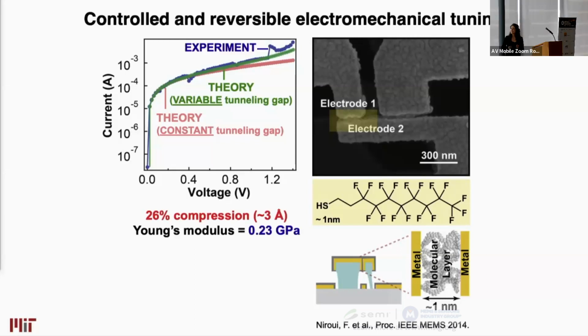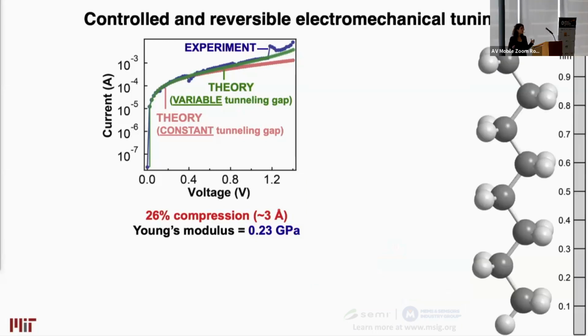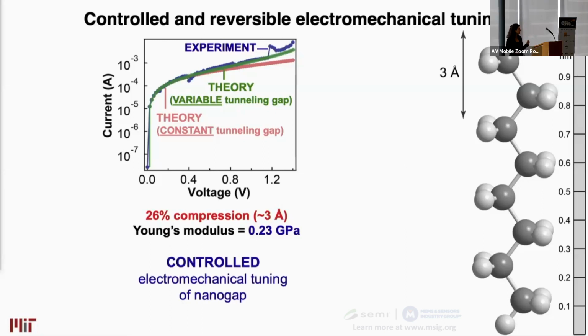Now, in getting this best fit, we estimate the Young's modulus of the molecular layer to be on the order of 0.2 gigapascal, which actually matches what you would expect for this molecule if you were to measure it through other experimental means. So in this process, the molecule undergoes about 3 angstrom compression in order to give you the 10 times modulation of the current. And to put that into perspective, that's on the order of 2 carbon-carbon bonds. So molecules could give you controlled modulation of very small dimensions.